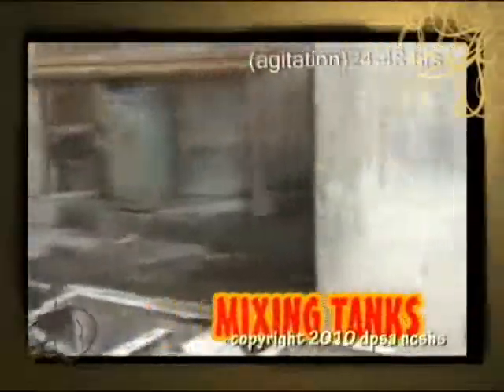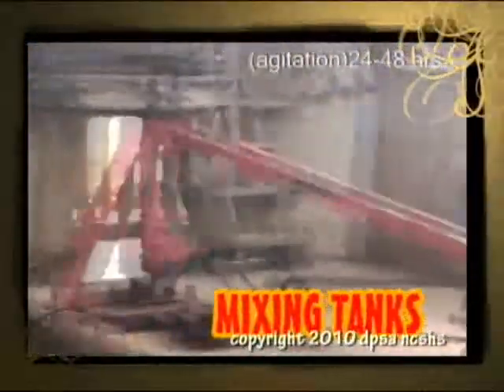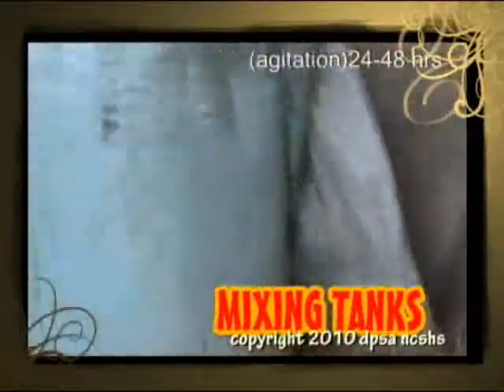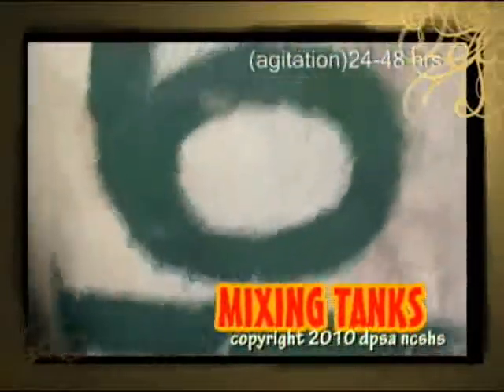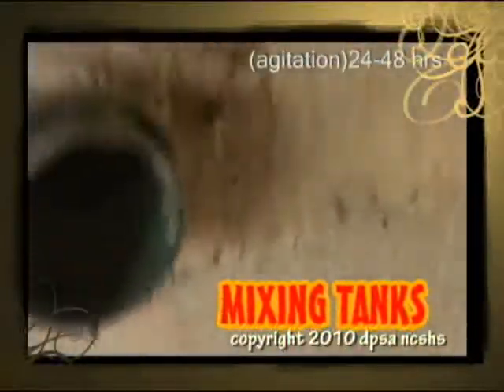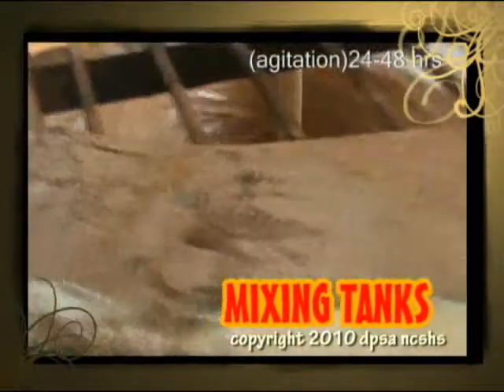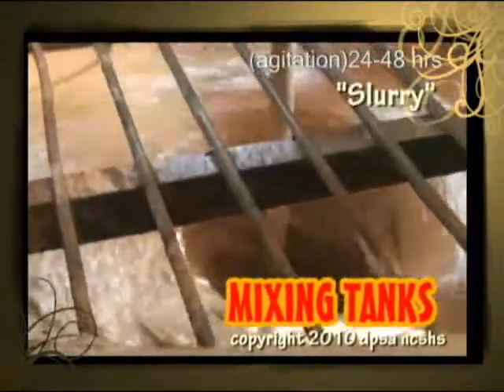The cyanide solution and the ore is now placed on the mixing tanks. Agitation takes 24 to 48 hours. The slurry or pregnant solution composed of cyanide dissolves the gold from the crushed ore. It can extract 95% of gold in the ore.